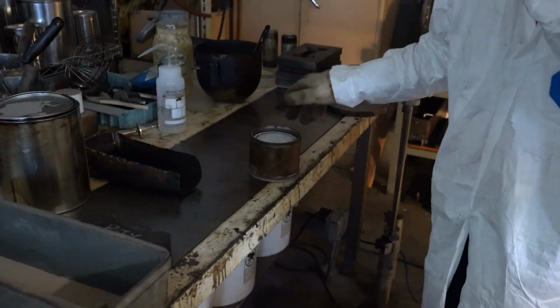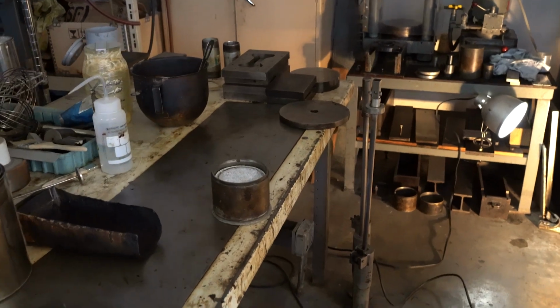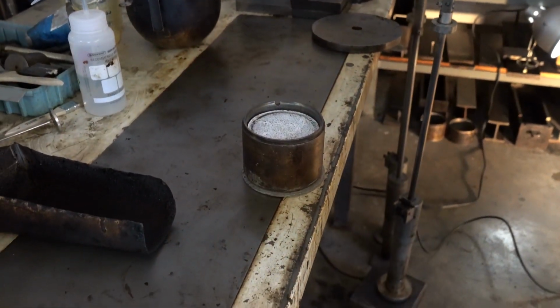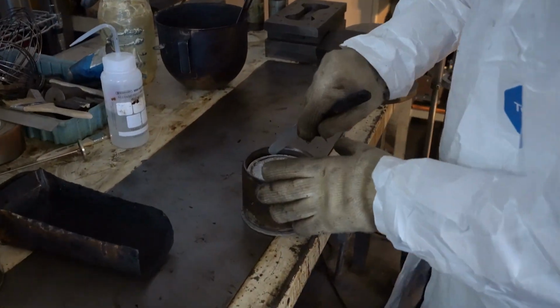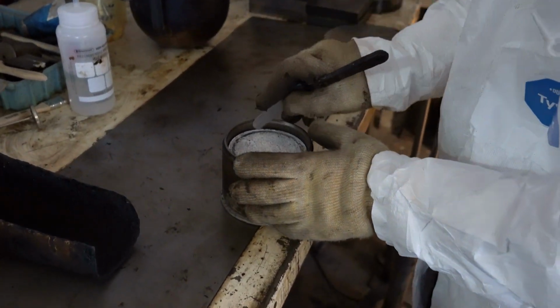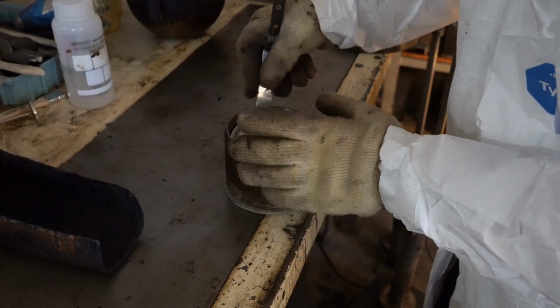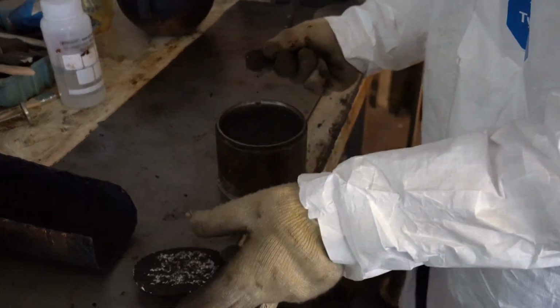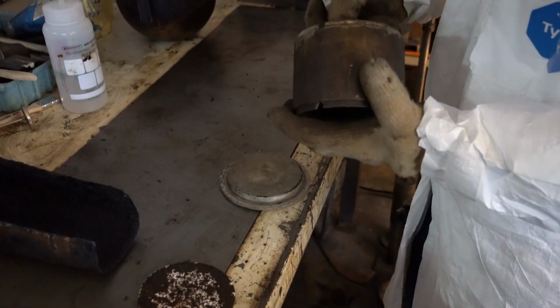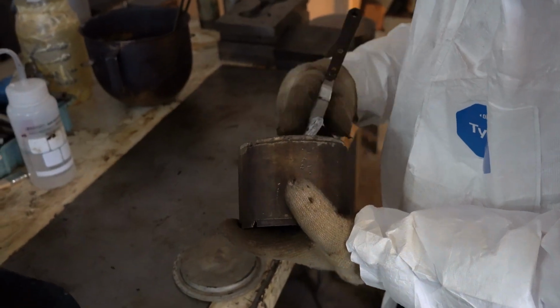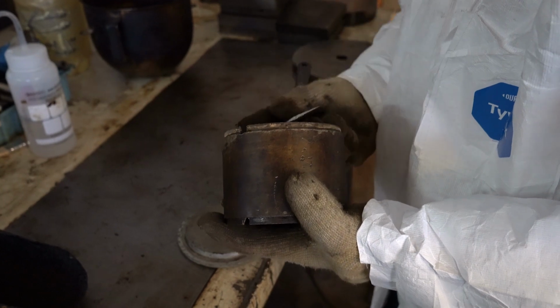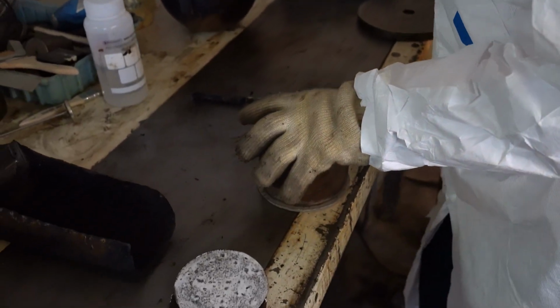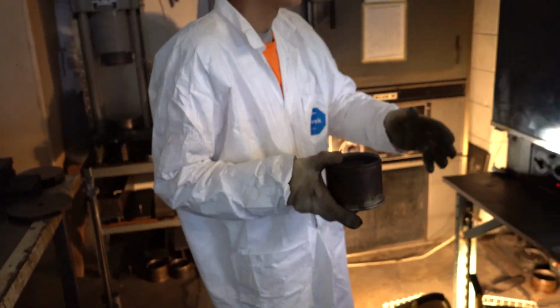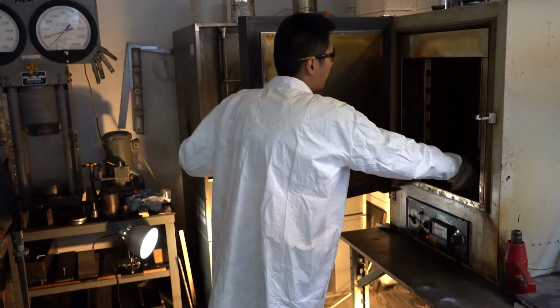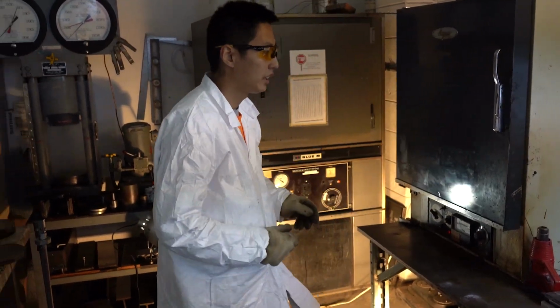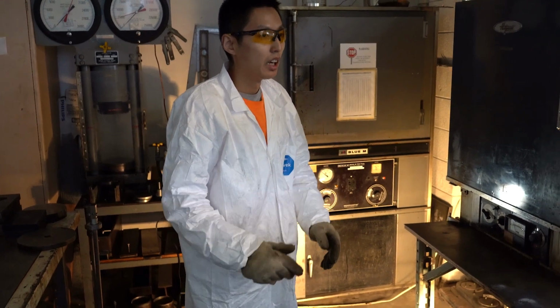Okay, this is the compacted sample. I take out the paper and go from both sides. We leave it in the oven for another 4 hours, just like Ms. Lau did for the liquid epoxy asphalt. We do the same thing, leave it in the oven for another 4 hours to reach the full cure strength.